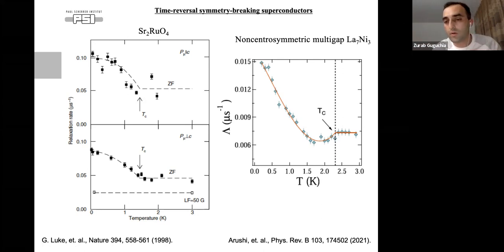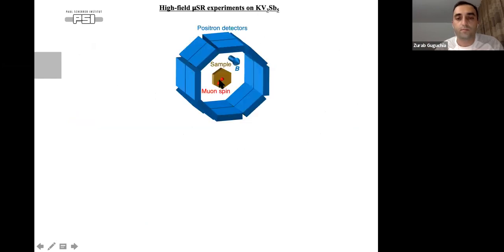Here also in the superconductors, they don't see an increase right below TC, but there is some kind of minimum and then an increase at lower temperatures, which was explained in terms of some kind of complex chiral superconducting state and so on. But at least experimentally, this kind of minimum was observed in different TRS breaking superconductors.